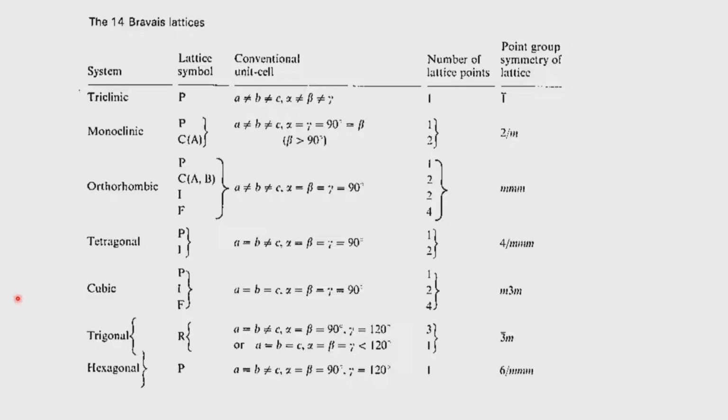So, in order to represent an object inside this unit cell, we need to have all these satisfied. Let us say a molecule goes into one of these crystal systems. The molecule will face the possibility of having any of these Bravais lattices. Depending on the Bravais lattice, the number of lattice points will change. So, the lattice associated with, let us say, the C centered lattice will have to have the same object also appearing with respect to the C centering. Here again, in the case of the F centered orthorhombic lattice, there must be 4 of those, and this is the way in which we have to associate the objects.